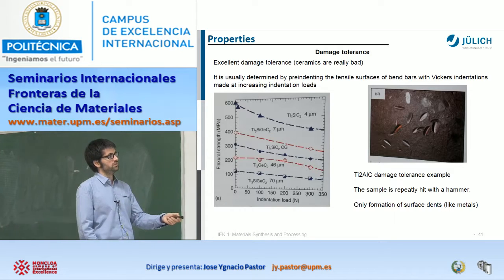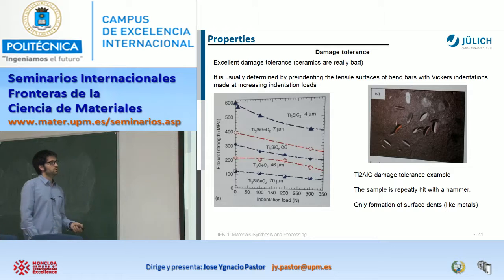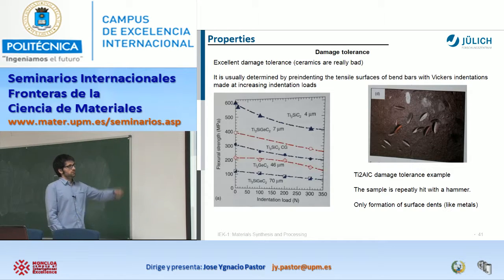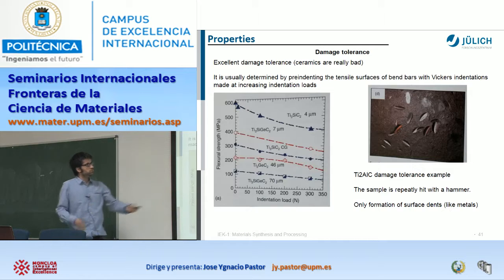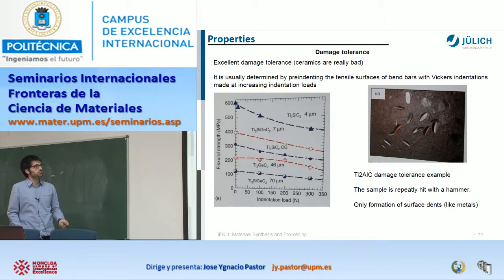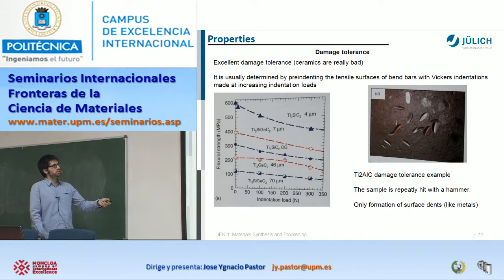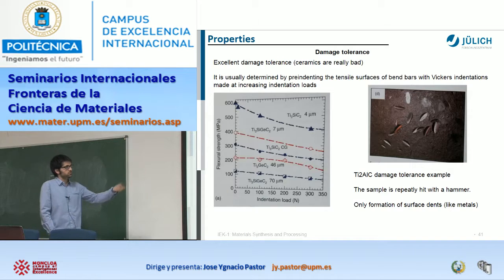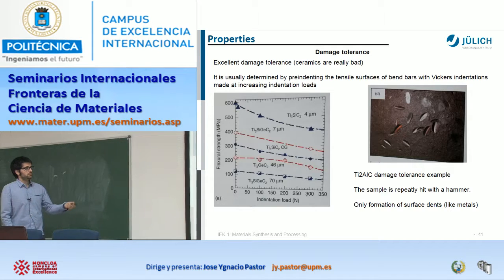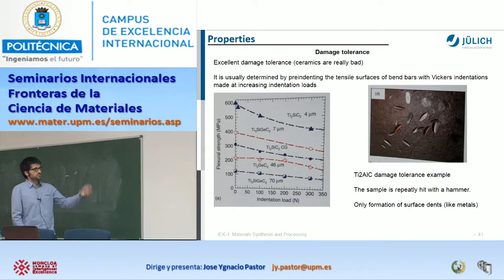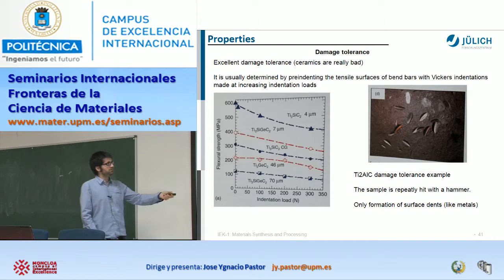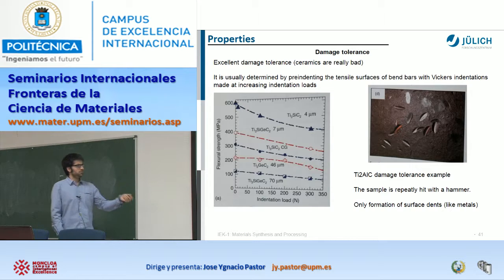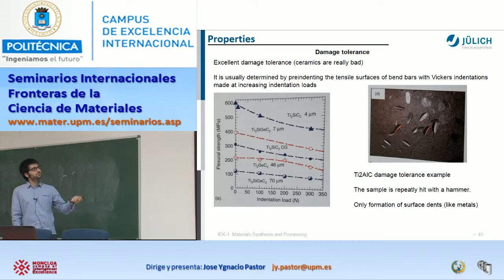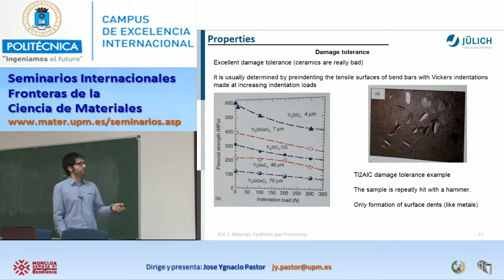And here is one example that for me is quite interesting, this titanium aluminum carbide that also presents an excellent oxidation resistance. If you hit it with a hammer, instead of breaking, it only responds like a metal. Of course, you produce something in your material like a deflection because they are soft, but they are not cracked. I mean, all the energy is absorbed by these kink bands and crack deflection, and then you can hit it and you will not break the material. It's like a metal. This is incredible. I took it from the book, but this sample was hit again and again with a hammer, and you just can do like that. Maybe you think that this is not quite interesting, but to be honest, if you do that in a ceramic, of course, forget it from the first impact.